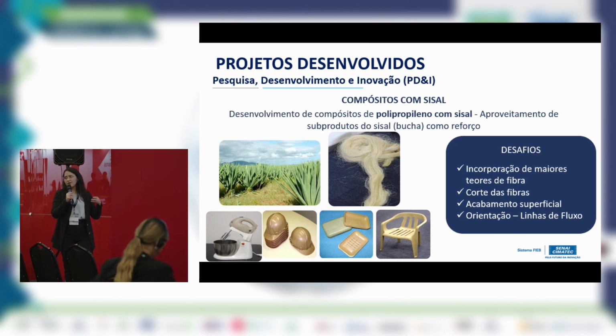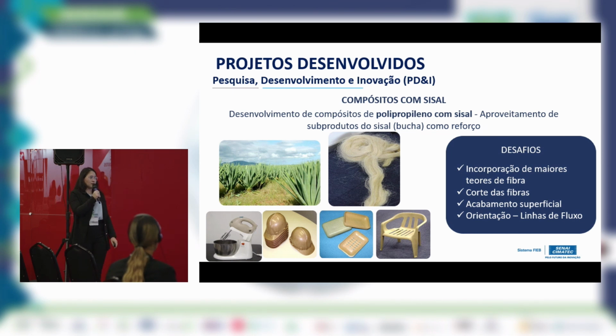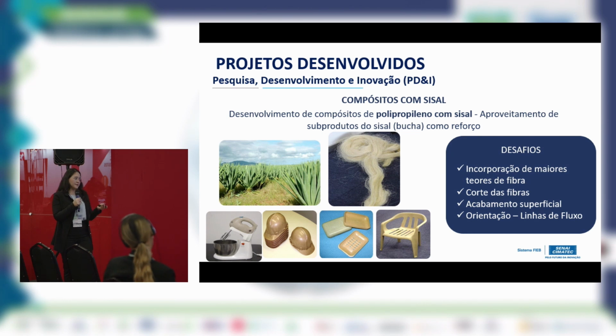The cutting of the fibers, we need to assess what's the best way to cut the fibers before using them and developing the composite. Superficial finish is an issue depending on the product. And in injection molding processes, because of the flow lines within the mold, sometimes the fibers take a certain direction and we don't have homogeneous properties, and that can be a challenge.